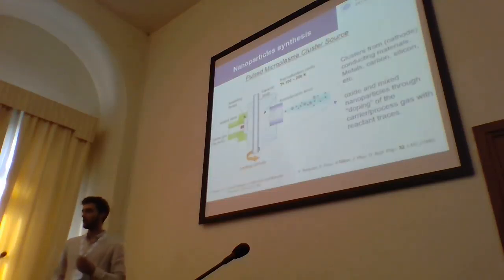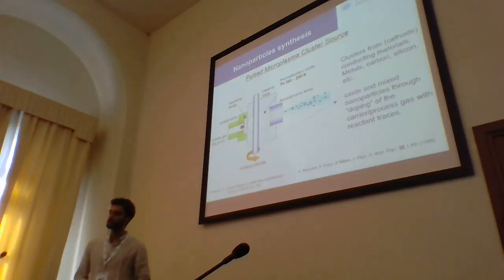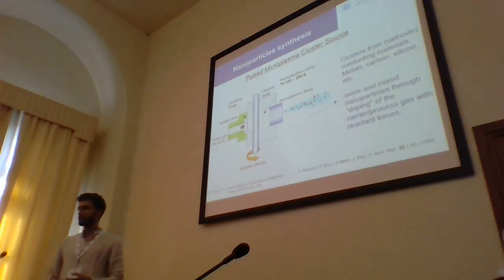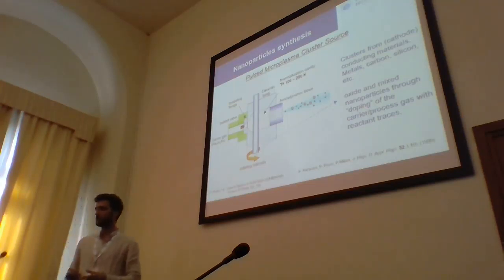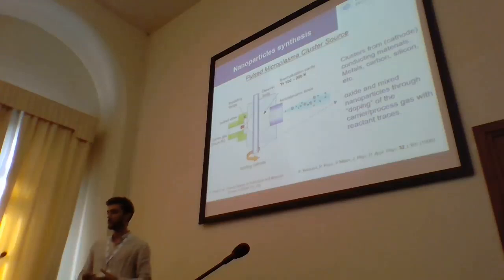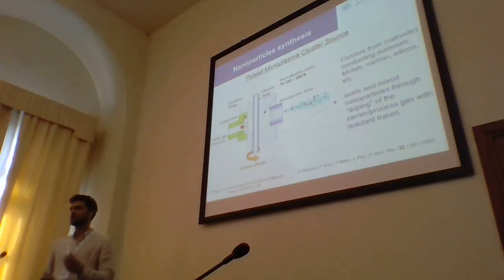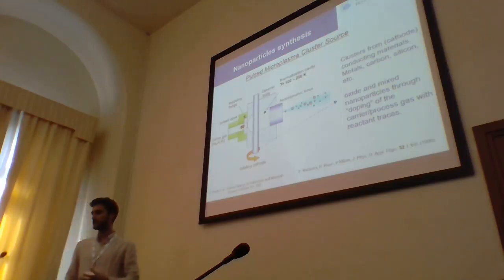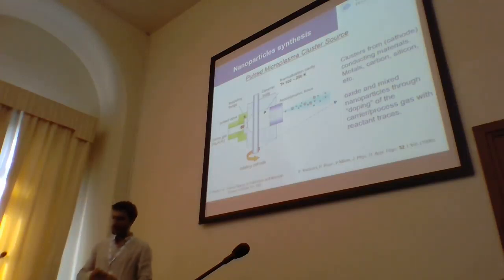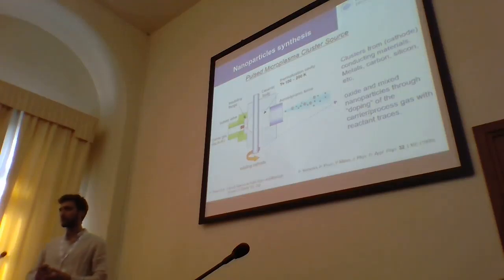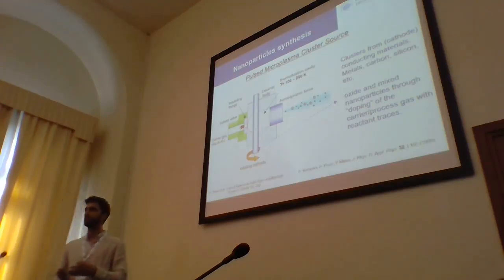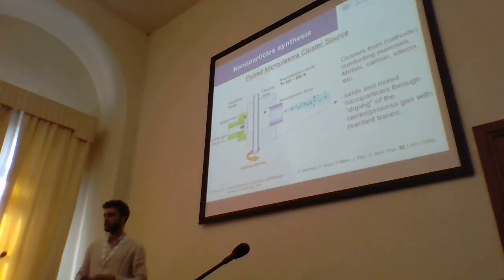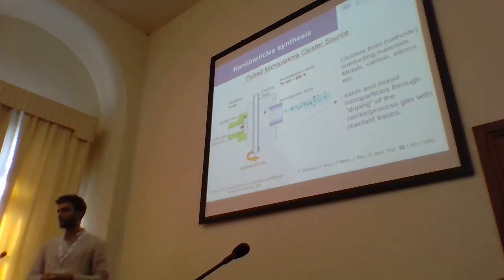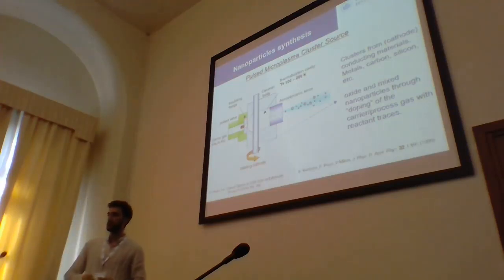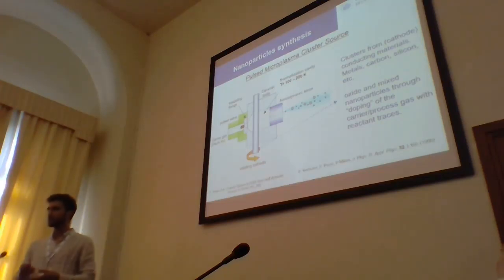So, very quickly, I used a pulsed microplasma cluster source that is made up of a ceramic body in which a metallic cathode is inserted. These cluster sources work in this way. We have a pulsed valve that injects a puff of a carrier gas, and a synchronized electrical discharge will ablate the cathode, creating a confined plasma that will erode the cathode, producing the nanoparticles that will be carried away by aerodynamic effects, basically. We can create oxide nanoparticles by adding a small amount of oxygen inside the carrier gas.